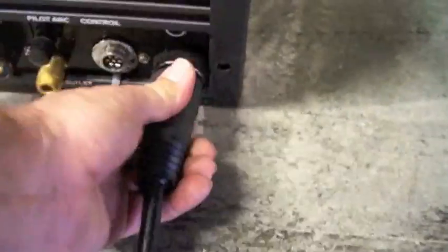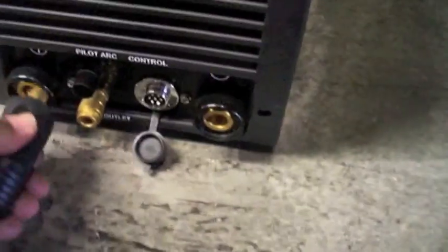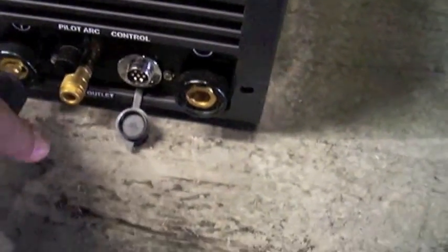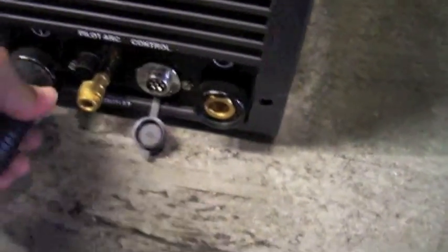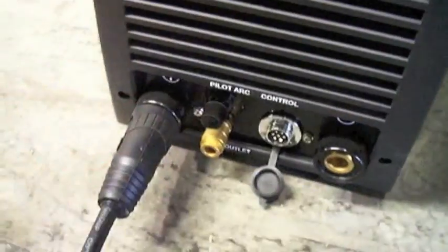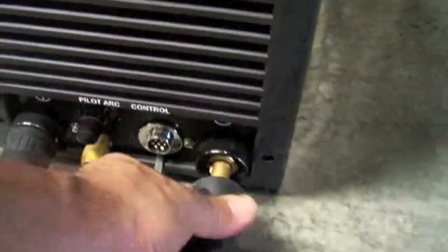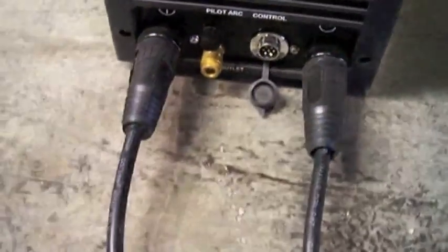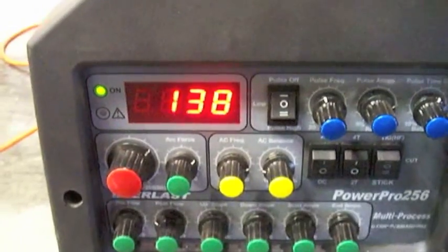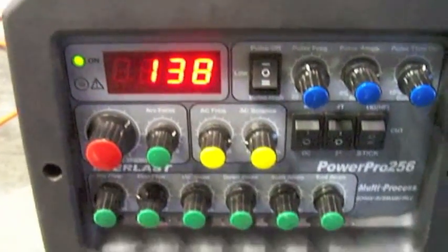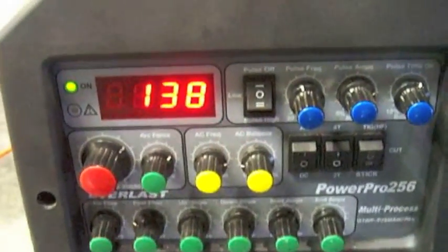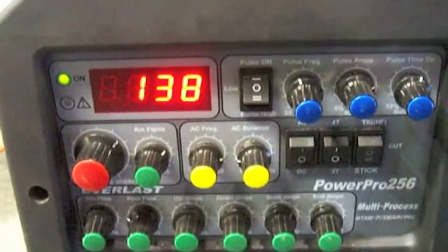Anyway, I also need to swap the electrode ground. Make sure I've got electrode positive for stick welding. It just takes a second. You can see it's pretty easy here because I'm actually holding a camera with one hand and doing it with the other. I settled in about 138 amps. I've got some 1/8th, 7018 rods.